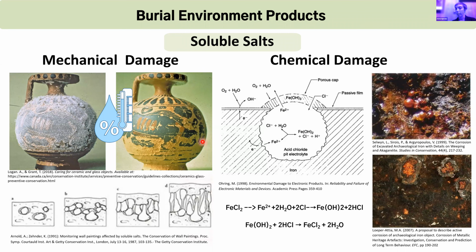Soluble salts are also very critical when it comes to continued corrosion activity that occurs even post-excavation, because a lot of those acid-base materials from the initial corrosion processes happening in the burial environment are producing salts. For iron, one of the most aggravating salts it produces is ferrous chloride. Ferrous chloride is a salt that, when exposed, even at room temperature, to atmospheric humidity, will basically go into solution, and then all of a sudden you have chloride ions hanging around.